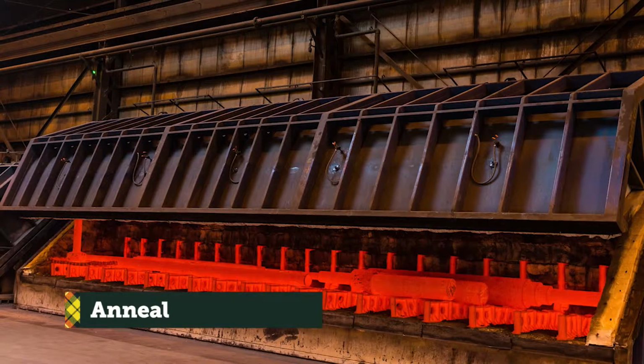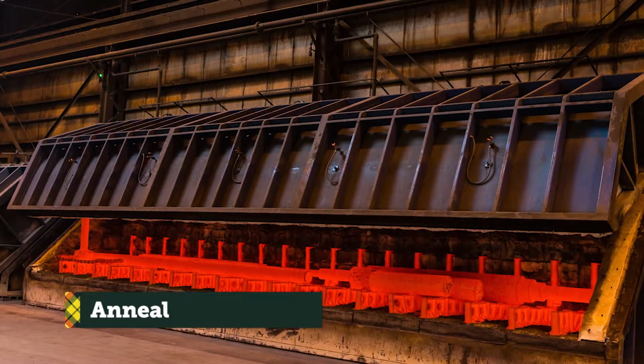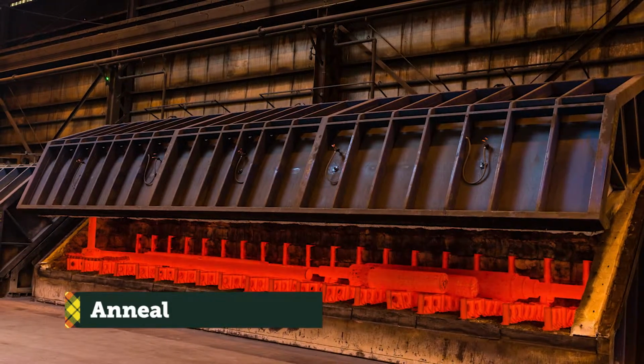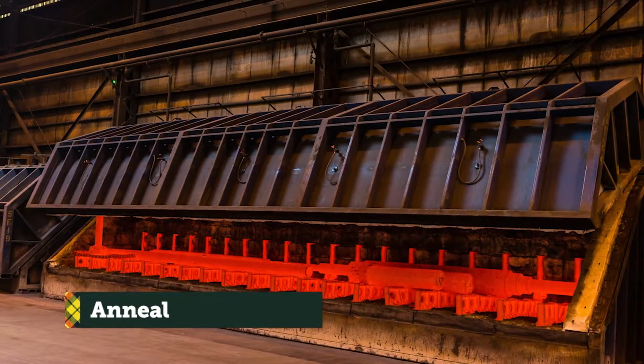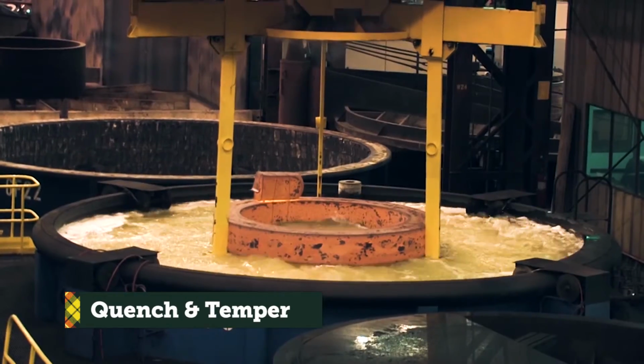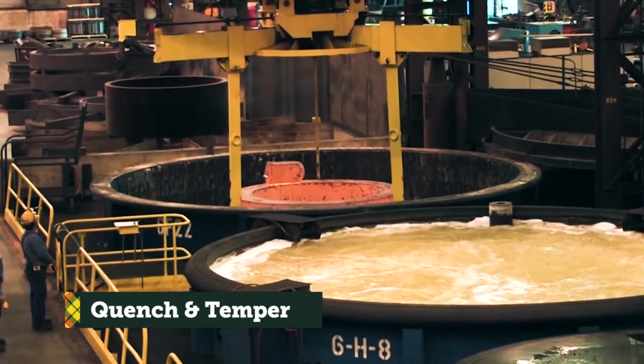An anneal is used to soften the piece. Oftentimes, customers are going to perform extensive machining after receiving the part from Scott Forge. This is often used before pre-machining that is completed prior to subsequent heat treat, such as a normalized quench and temper. In a quench and temper operation, this is where we're actually going to harden the piece and then try to dial in on a particular hardness range for you. We also use this to achieve particular mechanical properties.